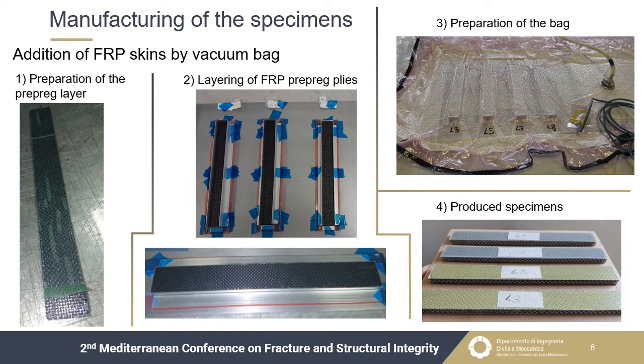All the layered specimens were covered with the release film and the breather fabric. Then the mold was closed with the vacuum bag. After the vacuum was drawn, the mold was positioned in the autoclave for the curing process.